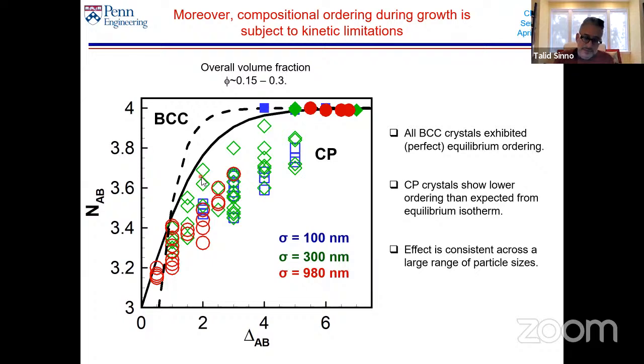That says that I'm being affected by kinetics. Just to give you a simple picture, if I have a crystallite and I have a particle attached in the wrong place, it can leave the wrong place and try again and come back to the right place. If I have an infinite amount of time to try out wrong and right places, I'm under equilibrium conditions. But since this thing is actually growing, I only have a finite amount of time to correct mistakes before I'm buried by another layer of particles. And so that's why there's a kinetic limitation.